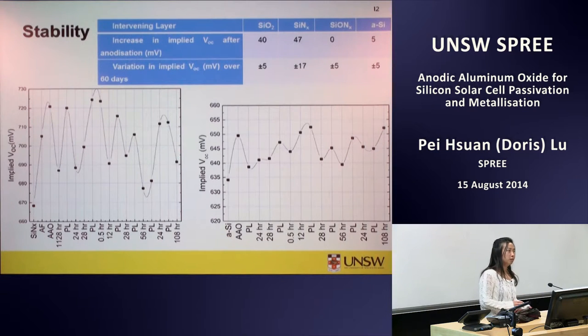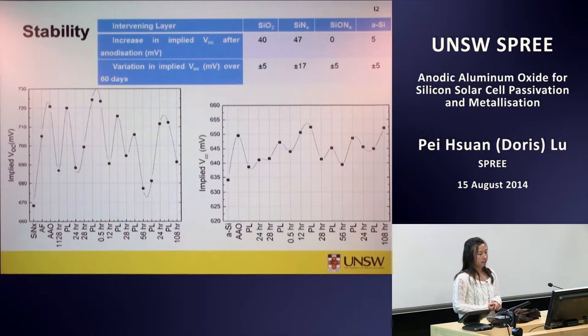So when people talk about passivation, we always think about the stability. It's interesting to see silicon dioxide and silicon oxynitride are much more stable with time compared with silicon nitride. For example, for this particular sample, after silicon nitride deposition, the implied VOC is 670. After forming anneal at 400 degrees in forming gas for 15 minutes, it increased to 705 millivolt. After anodization, another 15 millivolt improvement on top of it.